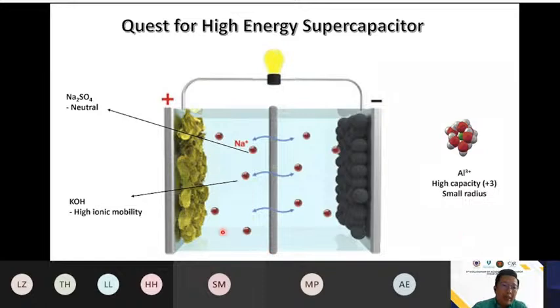Conventionally, scientists use potassium hydroxide due to its high ionic mobility, because the ions can move very fast between the two electrodes in the supercapacitor. But if you want to commercialize it, potassium hydroxide has a problem: it has a corrosive nature. So that's why people turned to sodium sulfate. The sodium sulfate itself is neutral, but the performance is not as good as potassium hydroxide. So in this case, we are putting forward the idea of using aluminum ions. The aluminum ions have a high charge of +3 and at the same time a very small radius, so we can have a high charge capacity within one ion. So we are going to investigate what kind of metal oxide can be used to capture this aluminum ion on the surface.